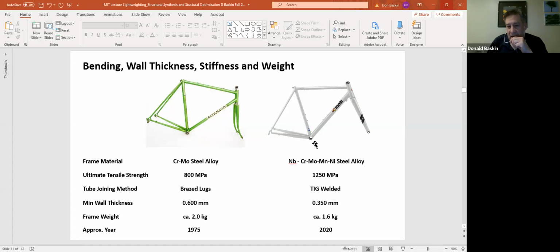On the right here is a Cinelli, also made in Italy, bicycle frame. This is a very modern frame. I believe they made it this year, so it's a 2020. In this frame, they use a more exotic steel than they do in the Colnago. They put a lot of niobium, relatively speaking, in the steel to refine the grain size. If you recall, this is one of the strengthening mechanisms we spoke about in the last lecture. Through putting in this niobium, as well as some chrome, moly, manganese, and nickel, you're able to produce a steel that has a much higher ultimate tensile strength at about 1250 megapascals or 1.25 gigapascals.